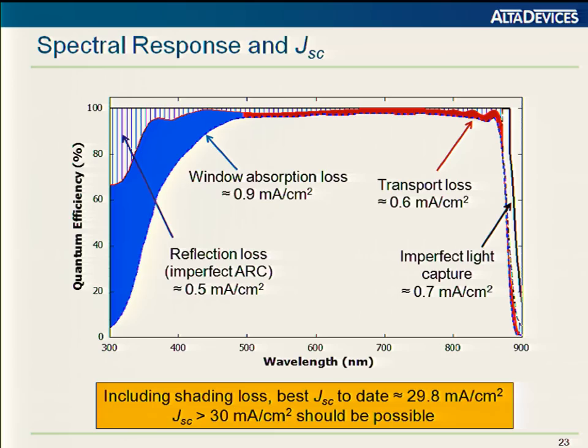Window absorption loss is used to describe the fraction of the spectrum that's absorbed in the front window of the cell but not collected as current. So you have relatively high recombination rate at the front interface of the window of the cell. Transport loss is the non-radiative recombination in transporting carriers through the cell. It's relatively small in our cell, but it's certainly not negligible entirely. And imperfect light capture is what I call the photons that hit the back reflector and make it back out the front of the device without ever being absorbed.